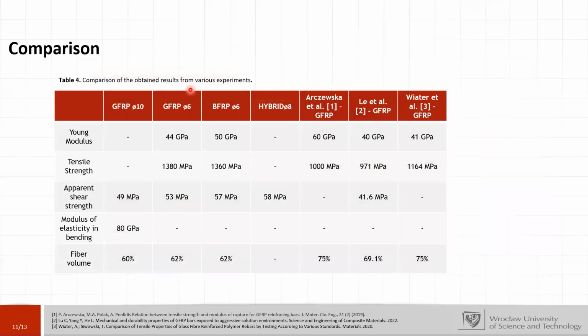Okay, so the comparison. I put here the results from our mechanical tests, as well as the results from the literature. And as we can see, the main advantage of our bars is very high tensile strength. It's about 1,400 megapascals, whereas in the literature I've noticed only about 1,200 megapascals. So that's quite a lot for the bars.